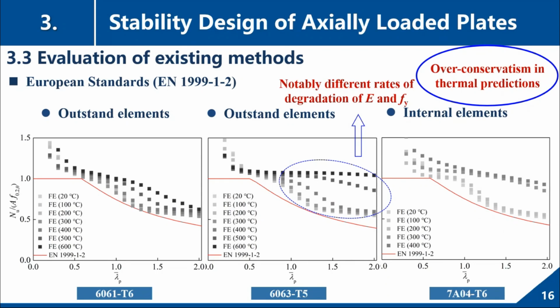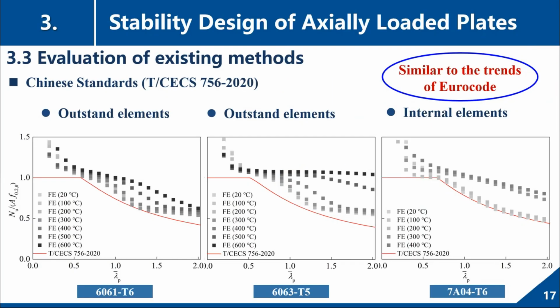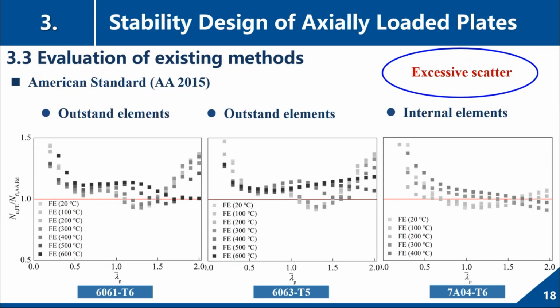We found that because of the different degradation rates of elastic modulus and yield stress, the accuracy of the Eurocode method is not good. It's over conservative. And then we evaluate the Chinese standard, because the Chinese standard is very similar to the European one. So the results are also similar. And then we assess the American standard. We found that although the accuracy is better, it is excessively scattered.